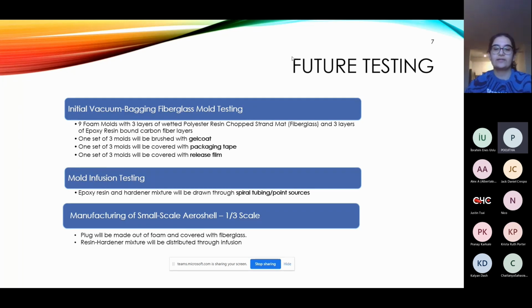The second test will be mold infusion, where 3 fiberglass molds will be prepared based on the results of the previous test. The epoxy resin and the hardener will be drawn through by spiral tubing and point sources, spread along the length of the part by vacuum bagging. This will refine our understanding of the infusion vacuum bagging process.